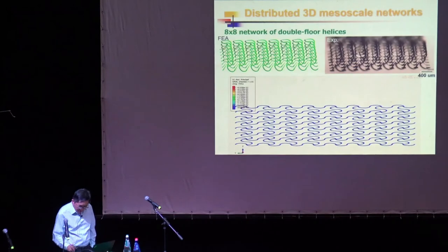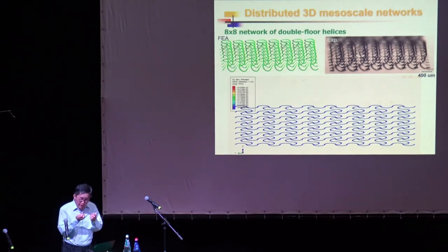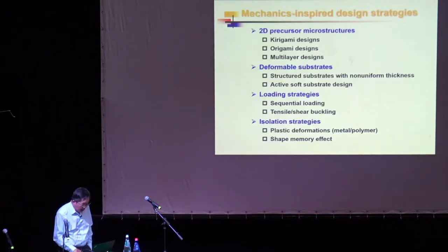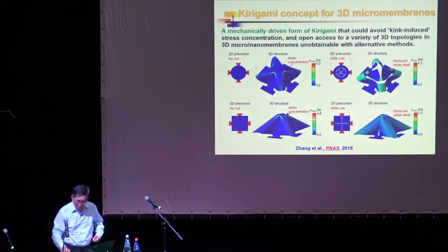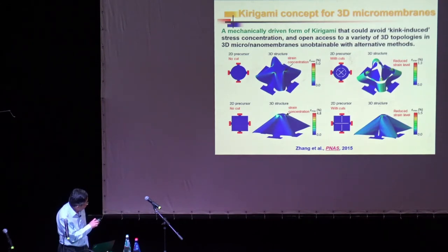When you look at those ribbons, very clearly you can see there's a lot of spacing among the ribbons. Your ribbons can rotate, can bend to reduce strain because there's not much constraint on the ribbon. They can rotate freely. However, when you deal with thin films, it's all compact together. When it deforms, they cannot rotate freely. It's constrained against each other. Therefore, strain concentration builds and silicon fails this way.